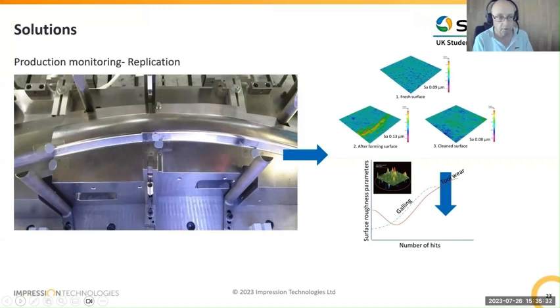And as long as we're reasonably consistent in where we're taking those replicas from, then we can monitor how the galling or any other wear which is taking place on the tool surface occurs. Now, like I said, for the most part, what we see is aluminium oxide transfer onto the die surface, which is what we call galling. And the best way of removing this is with a detergent caustic solution, because that dissolves the aluminium oxide.